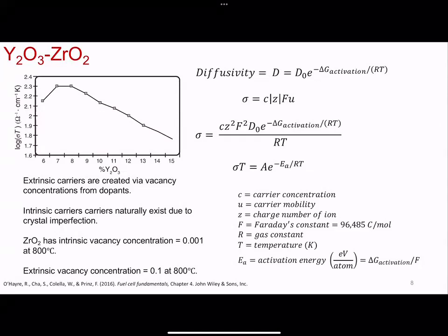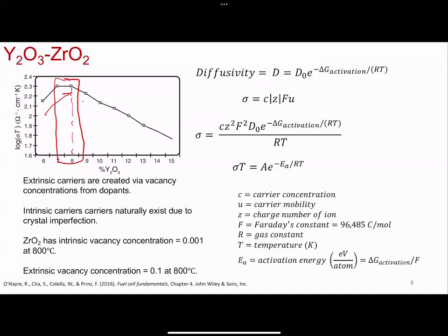People have done that. And you can see here that the more vacancies you introduce, the better, up until about 8. Here it's like 7.5, but somewhere in this range of substitution, mole percent of yttria, the ion conductivity will increase because of the increased vacancy concentration, and then it will decrease. So anything beyond this point is diminishing returns. That's my only econ reference, by the way. So yeah, there you go. And what you see, well, how do you measure this ionic conductivity?